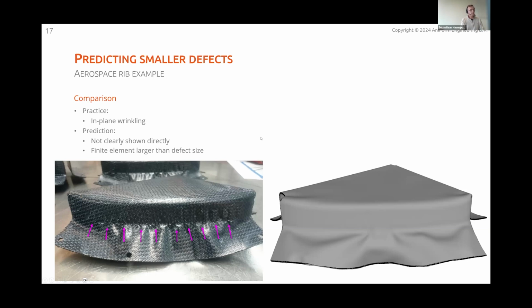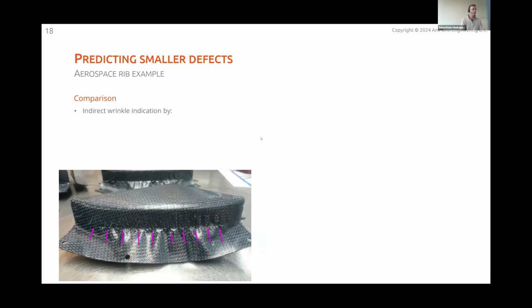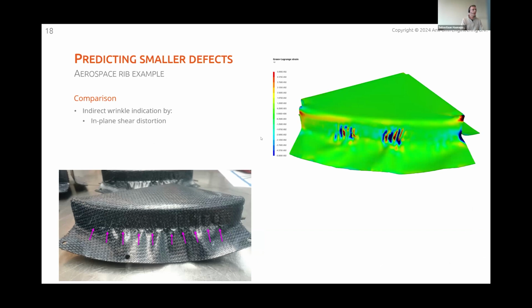Among other things, that is also simply because the finite elements are larger than the defect size, so things become a bit more complicated when it's about result interpretation. We can think about indirect wrinkle indication, for example, by looking at underlying results like the in-plane shear strains. And that picture is shown here. And we see at some spots here, these 2 spots, quite some irregular patterns of the in-plane shear.